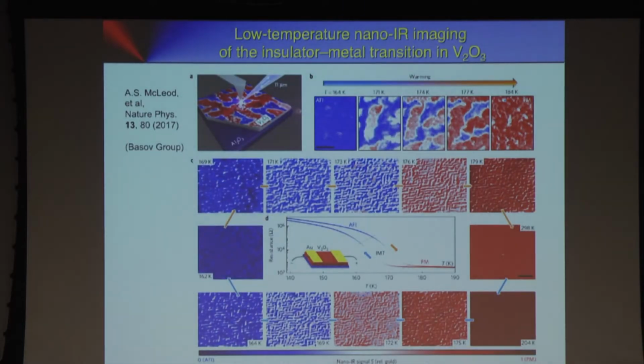And then very quickly, this is work from Dmitry Basov. They brought this to low temperatures. So the whole thing can be done at low temperatures. Maybe also interesting here, what they studied is, by heating up, V2O3, which is an insulator at low temperature and turns into a metallic phase. Everything that is red here is metallic, everything that is blue is dielectric, and they could see that nanostructures grow out during this phase transition, and this can be done at low temperatures. So also an interesting tool for material science.